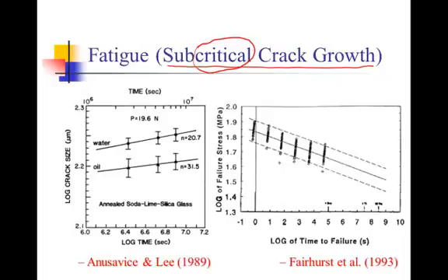The first one was conducted by Anusavice and Lee, and they used a micro-hardness indenter, a diamond pressed into the surface of dental porcelain to induce cracks in it. And then they watched those cracks every hour, and then every day, and then up to 2 weeks later, and noticed that the cracks slowly grew over time under an applied stress.